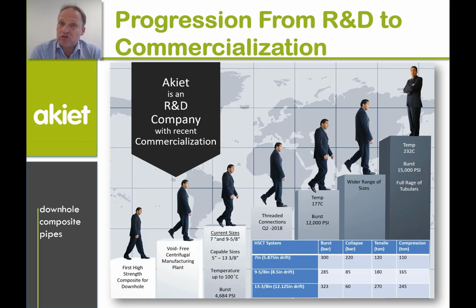Where we're currently constrained to around 100 degrees Celsius, we are underway with plans with strategic partners in a European subsidy project to raise that to about 170 degrees Celsius. And of course, with typical pressures that go with those temperatures as we drill deeper into the earth. So slowly and with continuing R&D, we'll increase the range and we will increase the performance of the tubulars. And where we stand now is tubulars in a few sizes up to 100 degrees Celsius.